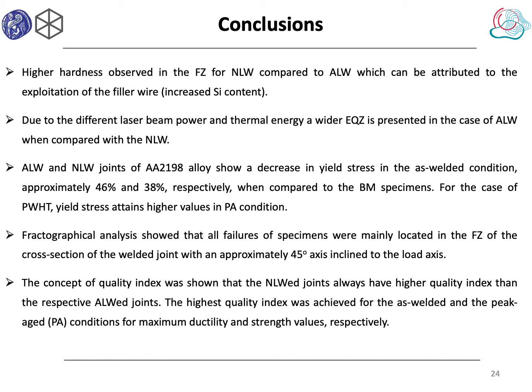Fractographical analysis showed that all failures of specimens were mainly located in the fusion zone of the cross-section of the weld joint, with an approximately 45 degree axis inclined to the load axis. The concept of quality index showed that non-autogenous welded joints always have a higher quality index than the respective autogenous joints. The highest quality index was achieved for the as-welded and the peak-aged condition for maximum ductility and strength value respectively.